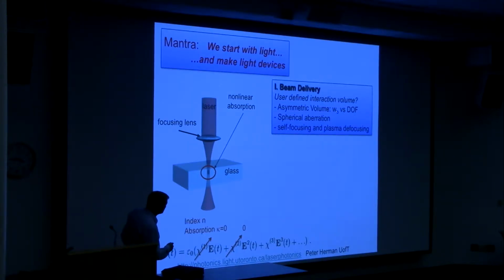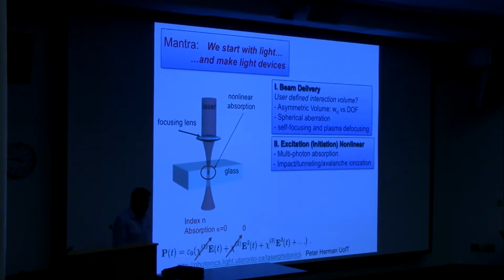Well, okay, we've got spot size omega naught and a depth of focus. It's not symmetric. That might be a problem that you need to counter by doing some beam shaping. When you enter a flat surface, you have something called, strangely, spherical aberration. So Snell's law breaks down and the focus gets distorted. So as you focus deeper, you have distortion effects. Before you get to the focus, you can get self-focusing. The focus position can move up, it can filament, and so even before you get to the focus, there are several distorting elements taking place. Next, as this intensity is rising in the focus, Chi3 has multiple modes of interaction.